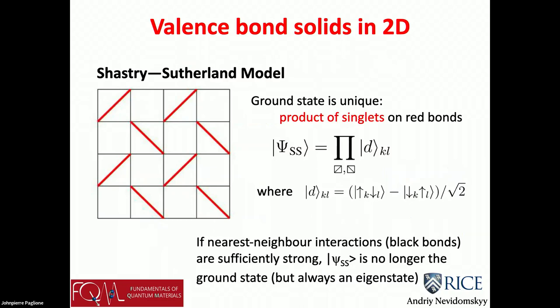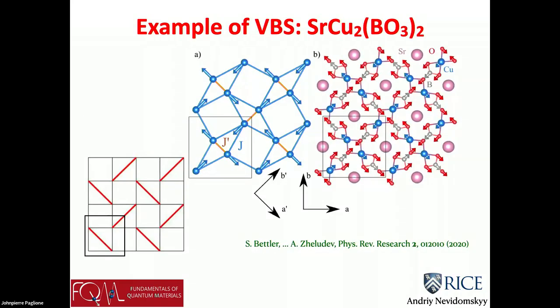You could try to do the same in 2D. So Sriram Shastry and Bill Sutherland were the first ones to propose this. And they showed that if you start with a system like this, where you ignore the black lines that just indicate that it's a square lattice, and imagine a compound that only has these red interactions, you could see that all spins are equally happy because they are happy to form dimers along the red bonds and be completely decoupled from one another otherwise. That's an example of a so-called product state. If you take a product state of dimers, each dimer is uncorrelated with one another. And in practice, once you add those black interactions, correlations do creep in, and that makes the physics much richer.